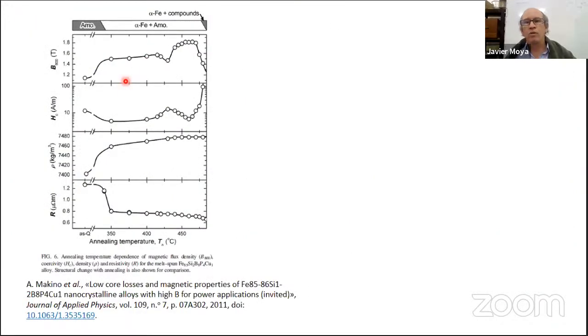To give you a better idea of our result, I found here a figure of Makino et al., where they show various properties measured in a nanomet type alloy. Here there are the magnetic properties, the density of the sample, and the resistivity. Here there are at least 16 experimental points, so it's implied that they used at least 16 samples to produce this result. They used, for example, one instrument to take this result, another instrument to measure the density, and another for the resistivity.